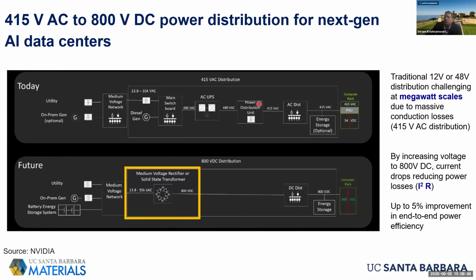By going from this 415 volt AC to 800 volt DC, one can dramatically reduce the conduction losses. Basically, you reduce the current draw, and so that reduces the I squared R loss. In the estimate that they worked out, that gives about a 5% improvement in end-to-end power efficiency, which is a big deal because 5% of a huge number is still a huge number, right?